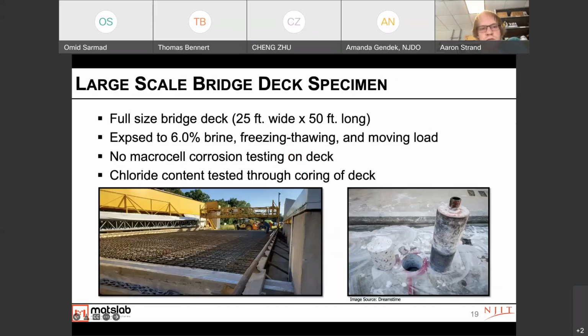So for the full large-scale bridge deck specimen that the laboratory specimens were helping to provide guidance on, it was a 25-foot wide and 50-foot long section, and it was exposed to a 6% brine, freezing and thawing, and also a moving load that went back and forth across the deck. So for this testing, we didn't collect any macrocell corrosion data. We collected the chloride content tested throughout, and so that was done through coring of the deck.